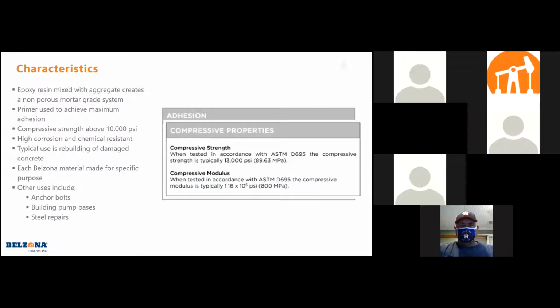Going into the characteristics, when you look at our epoxy resins, you're looking at compressive strength above 10,000 PSI. So we're going to outperform your typical concrete in compressive strength, compressive modulus, mechanical properties. Another good thing is we're going to use our primer. I think the slide underneath here has the adhesion numbers. We use a primer to achieve maximum adhesion. When we do our adhesion testing, we actually pull the concrete out. So what that says is our adhesion is actually greater than the cohesive strength of the concrete. So we're going to stick better to concrete than concrete is cohesively bonded to itself.